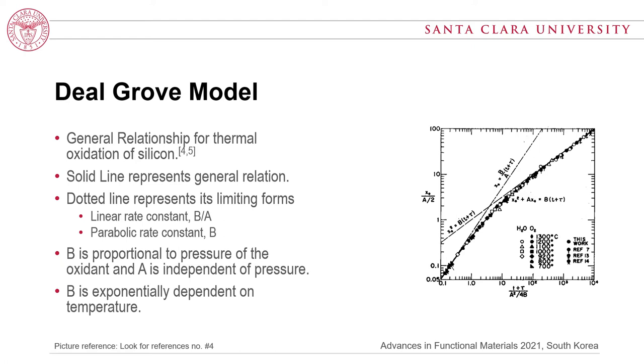The picture on the right provides a general relationship for thermal oxidation of silicon. On the x-axis, (t + τ) divided by A²/4B represents a time ratio, and on the y-axis, x₀ over A/2 is the normalized oxide thickness growth. The growth starts initially at a linear rate. After a certain time, the diffusion factor dominates, slowing the growth rate, which then follows a parabolic rate. In between these two states there is a transition, modeled as a combined linear-parabolic rate.